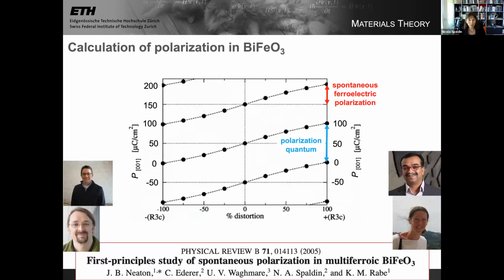Okay, so I want to show you then the first calculation of the polarization in bismuth ferrite, a density functional calculation of the polarization, to illustrate some of these concepts that we introduced at the start of the talk. And so this is work done in 2005 by Jeff Neaton, Claude Ederer, Umesh Waghmare, myself, and Karin Rabe. And what's being plotted here is the polarization. I converted it to the polarization in that 001 direction, perpendicular to the plane of the film, because that's what I want to discuss later.